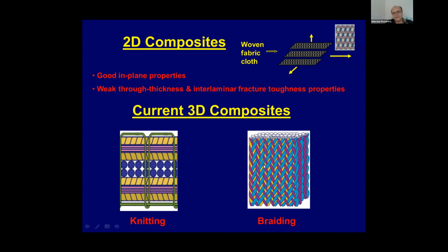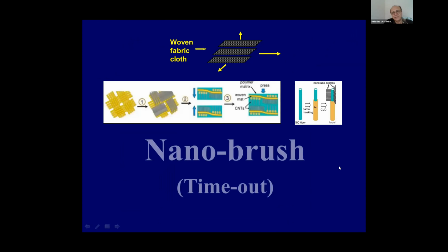In this case, also for braiding, you see the fibers are not orthogonal, which is normally what a designer uses, orthogonal fibers. And also, if you use a thicker laminate, you still have to put a number of these together. You get an interlaminar issue, which is resin rich.